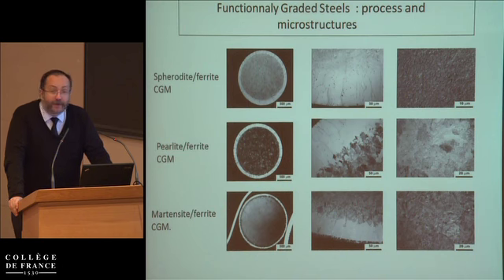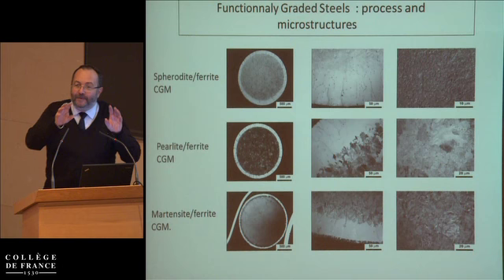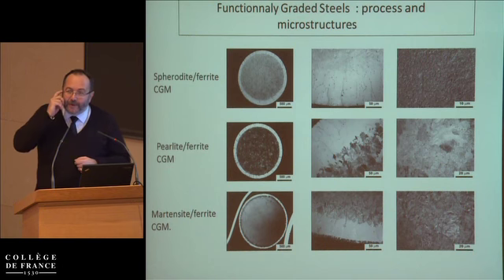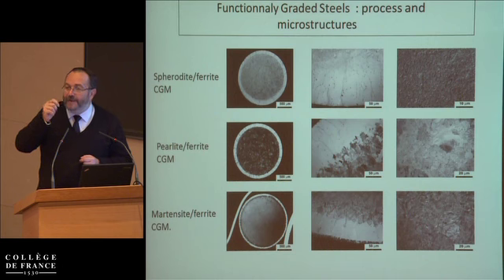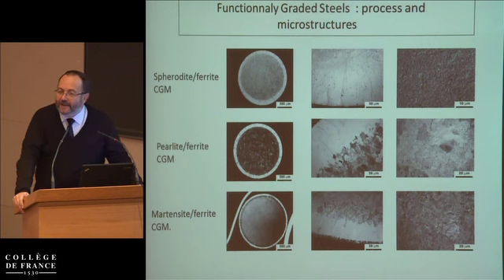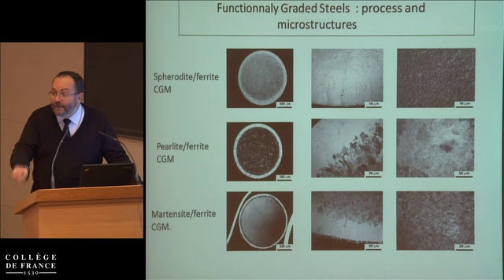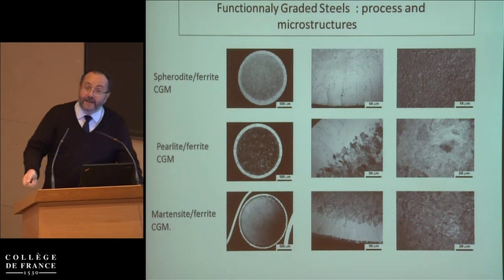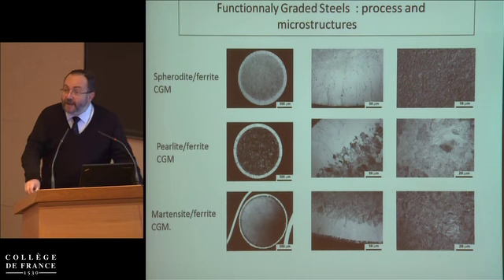And this one is the process by which you can make more ductile material, which is very strong, when the ductility is limited by the propagation of cracks from the surface. If you manage by phase transformation to have a soft layer at the surface, which is going to be a sort of protection, the crack is going to propagate inside the soft layer, and when it reaches the hard material, the crack has been blunted by its first pass, and you have material which is both strong enough, because you have kept the properties of the core, and more ductile, because you have killed the dangers of, for instance, the machining scratches on the component. So that's an example of an architectural material which is obtained here by phase transformation.